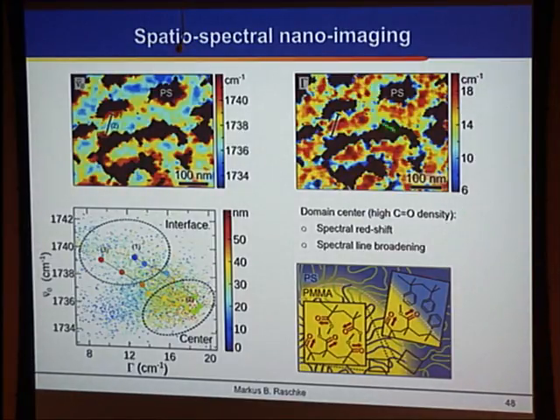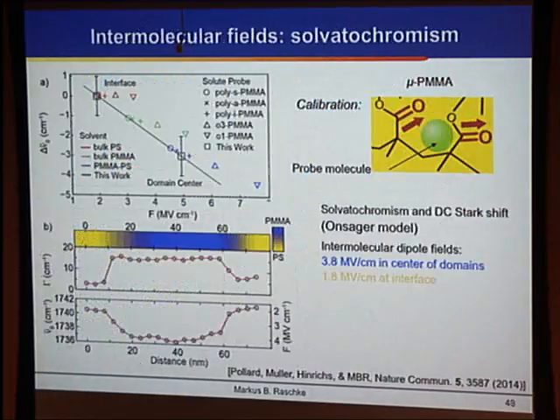And so we can then really quantitatively analyze this picture and determine that at these domain interfaces, over a few tenths of a nanometer distance, we get this rapid change in line width, really over molecular scales, as this coupling greatly decreases, which leads to this line width narrowing and to that corresponding shift in frequency, which we use as a metric of the change in this intermolecular field strength. And you see that over a distance of 10 nanometers, the intermolecular field really changes from about 4 megavolts per centimeter to 2 megavolts per centimeter.